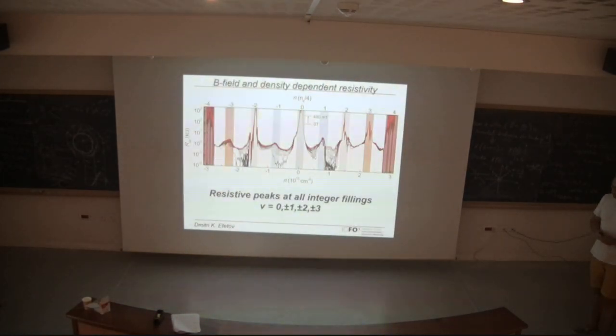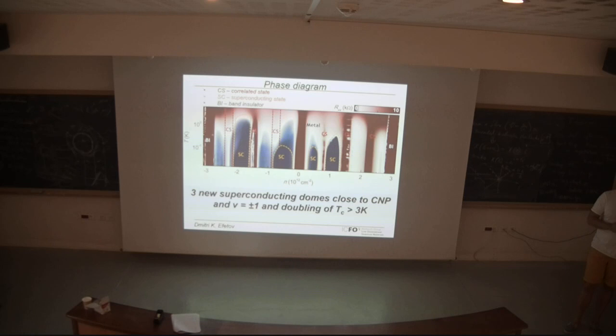Now, as you can notice, in regions between the insulating states, where the filling is not integer but some fraction in between the integers, resistance in many regions drops basically to 0. Between here, -3 and 2, resistance goes to very low values. These are new superconducting states which we observe. And the picture is a little bit more complicated than just these two ideal superconducting states close to -2 and +2 filling. We actually observe a variety of superconducting states.